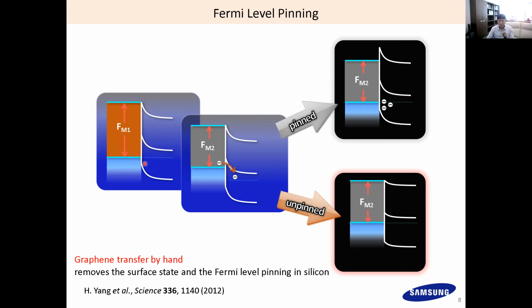In graphene, we know we can modulate the work function by this 2D nature. And by my STM experience, I know we can passivate the surface state. To compensate the broken symmetry at the top surface of the silicon, what about passivating the silicon atoms with hydrogen atoms? So we have Si-H bonding. We can keep this structure and remove the surface state. But the problem is the hydrogen atoms are removed by metal deposition, but I put graphene by my hand. So I could keep this hydrogen structure and keep the surface clean. That was a key concept in vertical heterostructure 2D devices in the beginning stage.